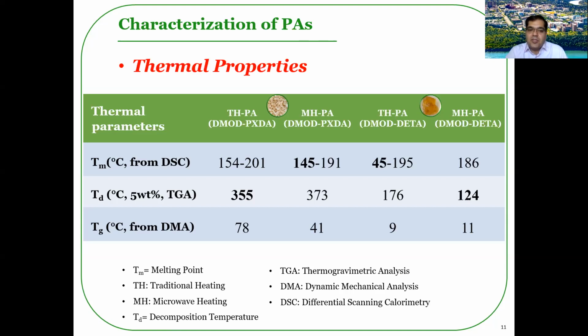Regarding the glass transition temperature of the polyamides, different heating methods had significant effects on the TG point of the semi-aromatic polyamides, while they didn't have almost any effect on the TG point of the linear polyamides. Therefore, the traditional polycondensed semi-aromatic polyamides had a TG point as high as 78 degrees centigrade, while the microwave polycondensed semi-aromatic polyamides show a TG point around 40 degrees centigrade. And the linear polyamides had a TG point around 10 degrees centigrade.